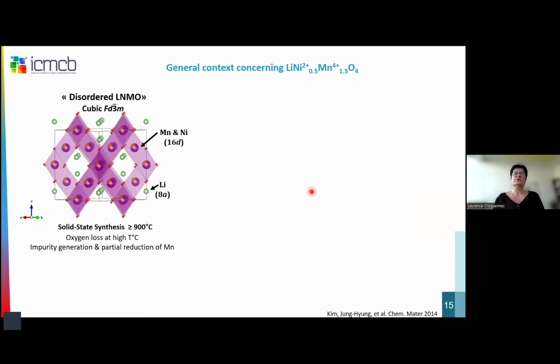So then if we come to the structure, these materials are based on cubic structures, the spinel type structures, and we have in fact two structures for these materials. We have disordered structures, so it means that here on the octahedral sites of these spinel structures, we will have manganese and nickel that will be statistically distributed, whereas lithium will sit on tetrahedral sites. So this polymorph is obtained at a temperature higher than 900 degrees when we do the synthesis at these temperatures.